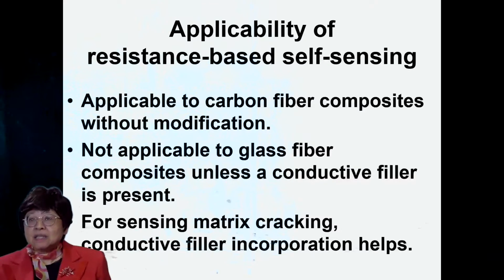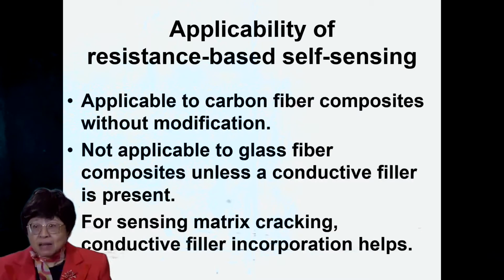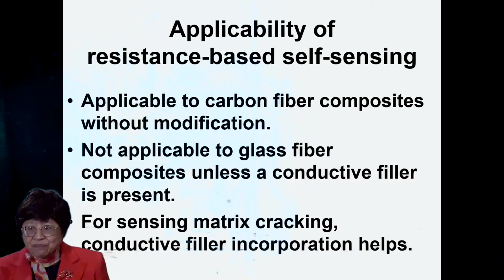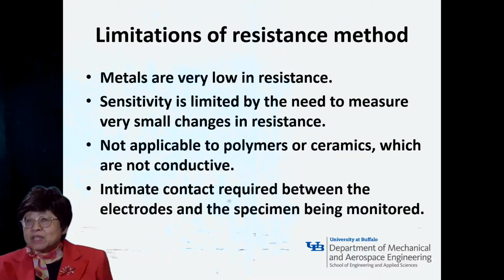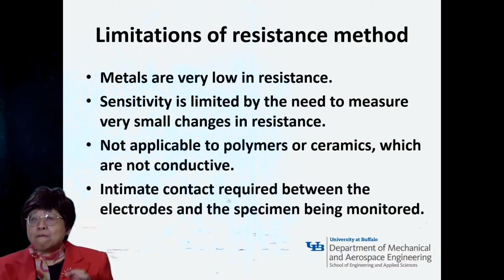The application of resistance-based self-sensing is good for carbon fiber composites without modification because it's already conductive, but it's not applicable to glass fiber composites unless a conductive filler is present. So that means modification. For sensing matrix cracking, conductive filler incorporation would help. Resistance measurements, though, has limitations. Metals are very low in resistance, so sensitivity would be limited by the need to measure very small changes in the resistance. And also, it's not applicable to polymers or ceramics, which are not conductive. Also, one needs intimate contact between the electrodes and the specimen.